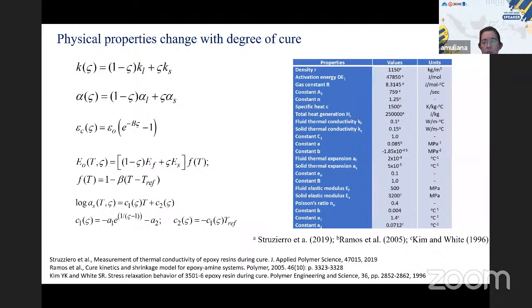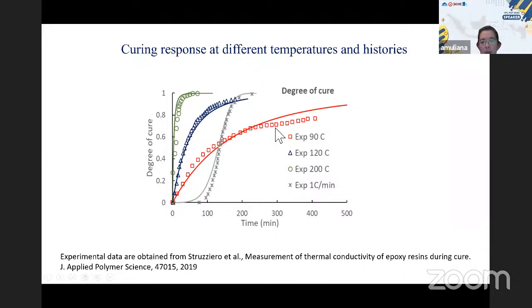So what I'm trying to show here is that when you change the temperature, right? From low temperature to high temperature, as you can see here, at high temperature, it can cure faster. At low temperature, for example, this is at 90 degrees, even after you wait like 400 minutes, it does not fully cure, right? Another way, we could also apply relatively low heating. So this is when you ramp the temperature 1 Celsius per minute, compared to what we call isothermal curing, where you just heat it up to the very high temperature without controlling the heating, right? So this will have all different effects on the polymer curing.